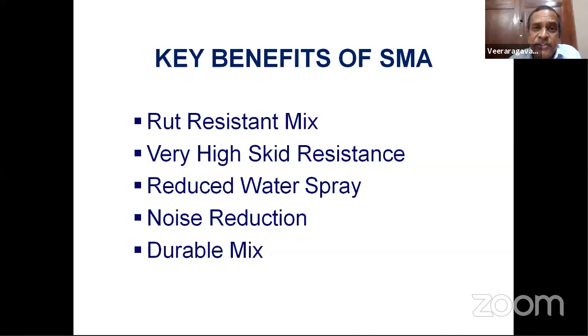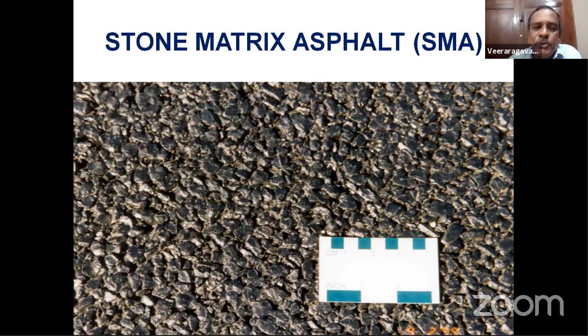On expressways, I strongly believe the surface should be SMA, no bleeding will occur. It offers a very high skid resistance, reduced water spray, reduced noise, a durable mix, but it's costly because the minimum binder content is higher than the BC. We use cellulose fibers and polymer modified binder, so it may cost over 50% more than the BC, but it lasts longer. So this is how a surface will look like. These are the new technologies that we need to adopt, especially in the case of expressways.